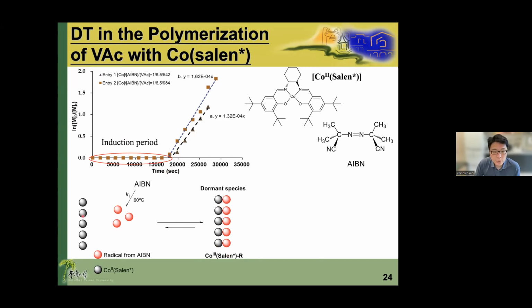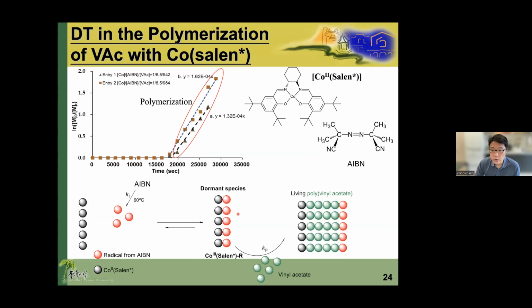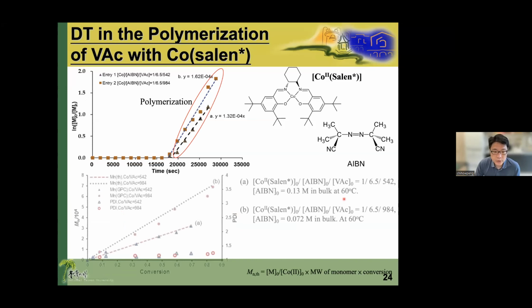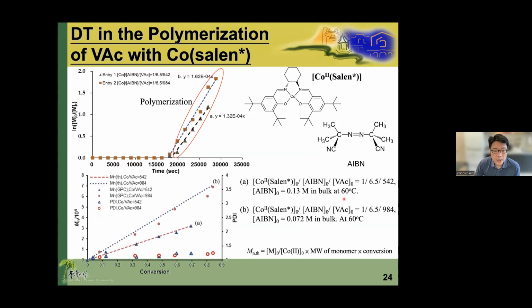But once all cobalt(II) was converted to the organocobalt(III) species, then the following radical will not be trapped, and it can initiate the polymerization to give you the living polyvinyl acetate. So according to the instrumental analysis, you can see the polymer has the molecular weight increasing linearly with conversion and relatively low polydispersity. And we calculate the theoretical molecular weight based on one chain per catalyst, meaning all the polymers have one cobalt species at the chain end.